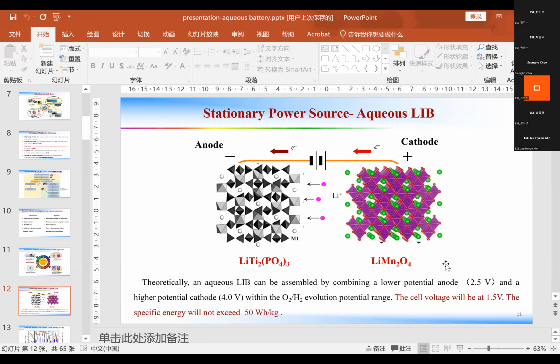So first, let me talk about the lithium-ion battery, the aqueous lithium-ion battery. Theoretically, an aqueous lithium-ion battery can be assembled by combining a low potential anode material, with a potential like 2.5 volts, and a higher potential cathode material, with a potential about 4.0 volts versus lithium, within the oxygen and hydrogen evolution potential ranges. So the voltage will be 1.5 volts. And then we can count the specific energy will not exceed 50 watt hours per kilogram. This is based on the practical batteries. So the specific energy density is closer to the lead acid batteries.